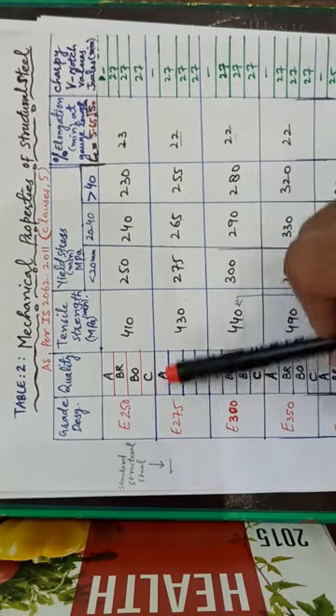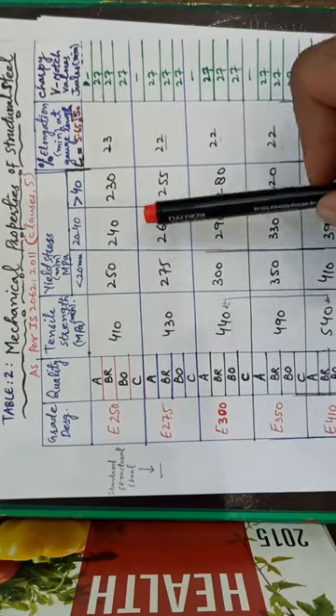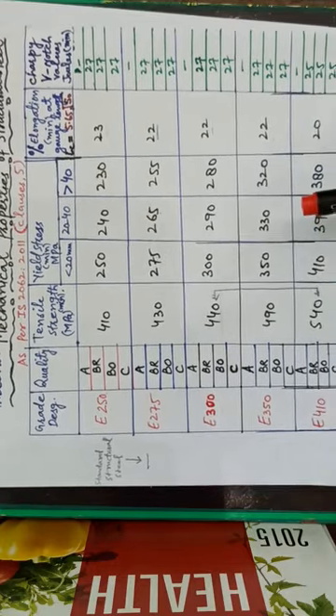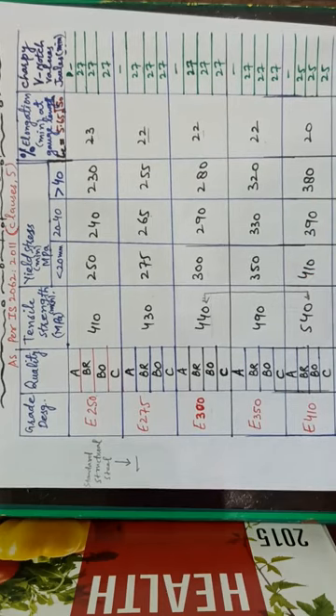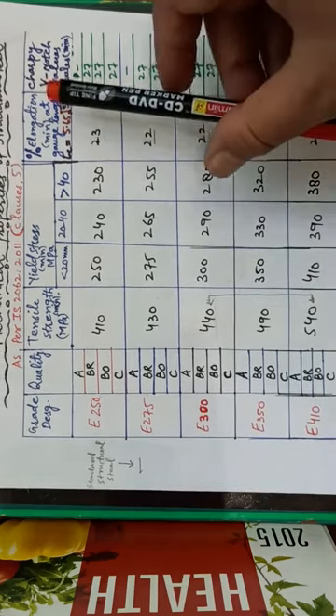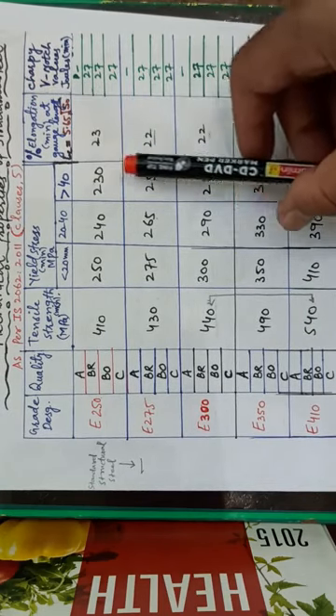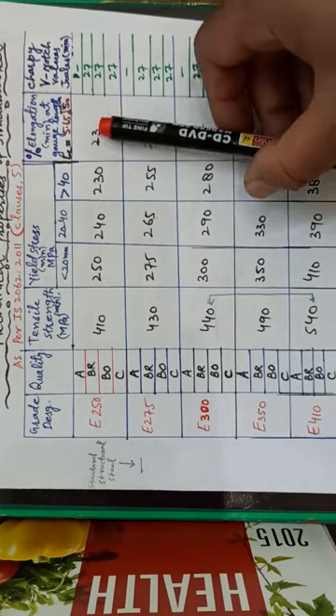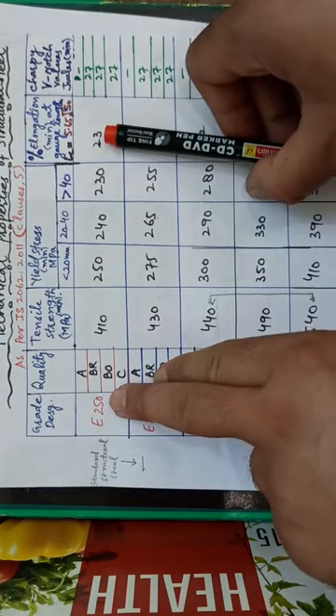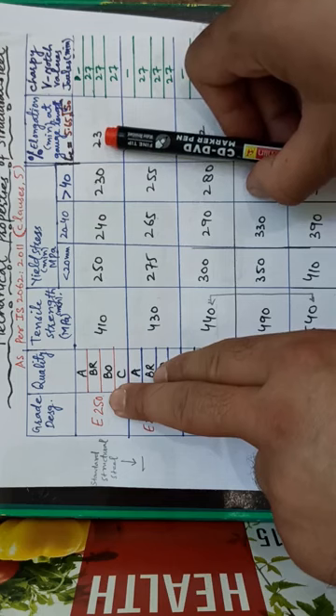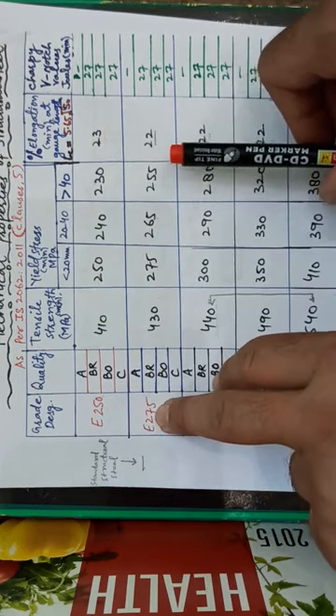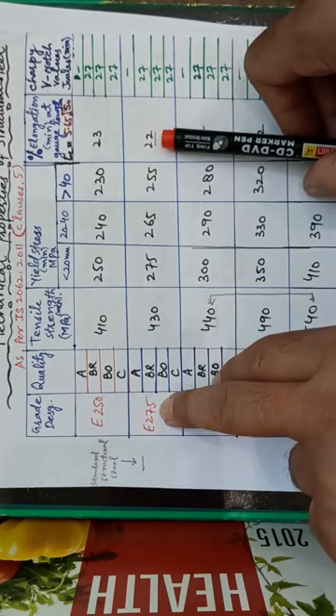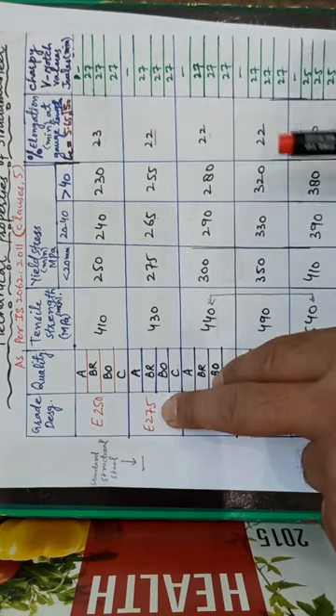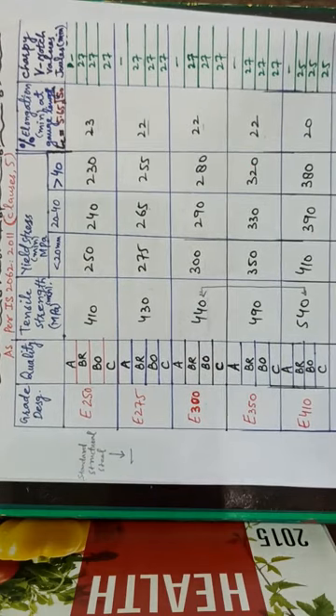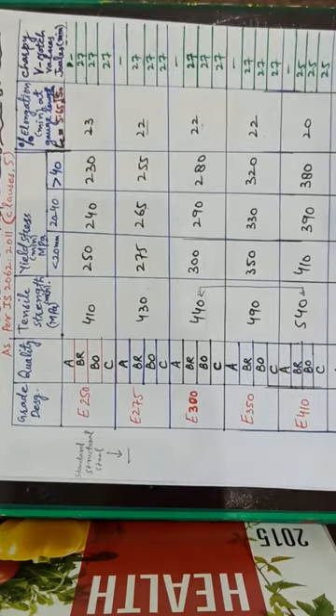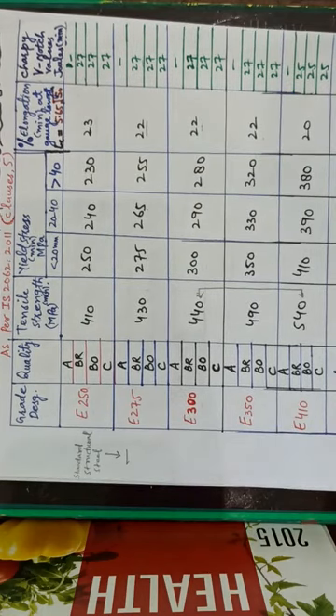Similarly, for other grades of steel, we have the tensile strengths as well as the yield stresses for different thicknesses given. And the percentage elongation at a specified gauge length is given too. For example, for E250 grade the minimum percentage elongation is 23, and for E275 the minimum percentage elongation is 22. Similarly, for different grades you have the minimum percentage elongations given in IS 2062.